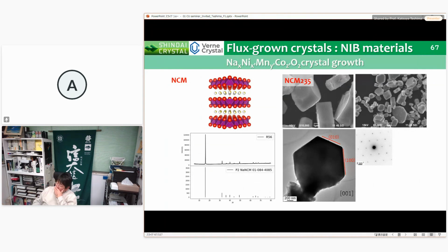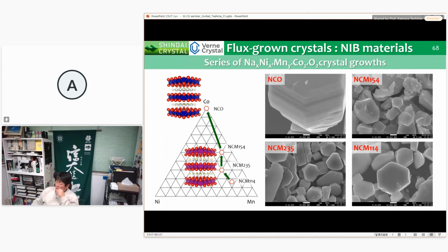These are the identification results for NCM235 crystals, and it has been confirmed that similar low aspect ratio crystals were obtained. As for ternary systems, we have been working on growing 3 types of crystals: NCM154, 235, and 114. All have P2 type crystals, and we have succeeded in achieving low aspect ratio for NCM154 and 235. We are currently expanding the scope of crystal control to other layered oxide systems.